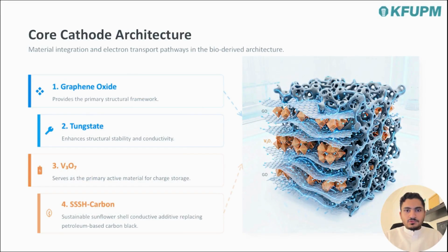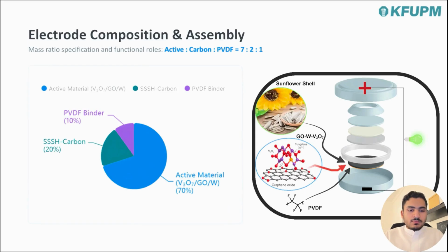Thank you, Mohammed. To test this idea, we designed the cathode with specific material characteristics. The components are graphene oxide sheets, and in between them we have tungstate intercalated vanadium oxide in addition to sunflower shell carbon. The mass ratio of our electrode composition is 70% from the active material, 20% from the sunflower shell, and 10% from the PVDF binder.